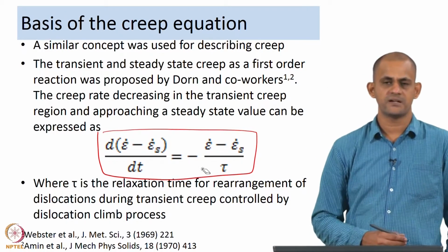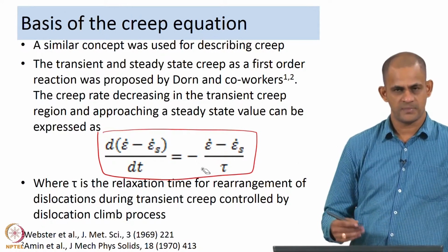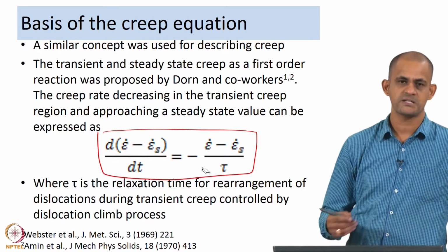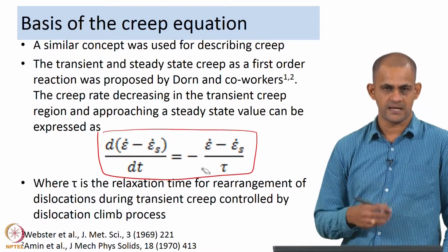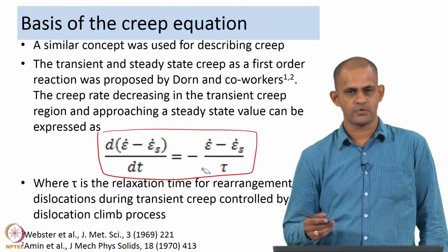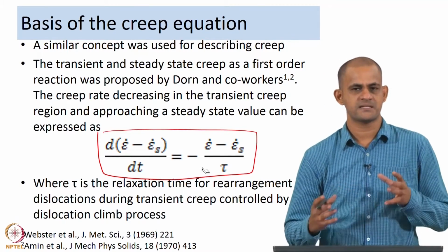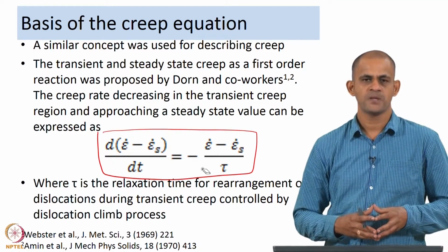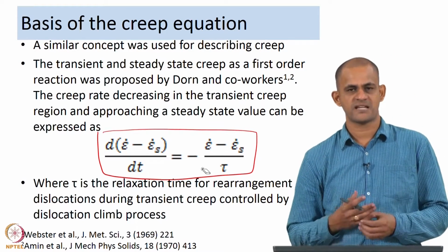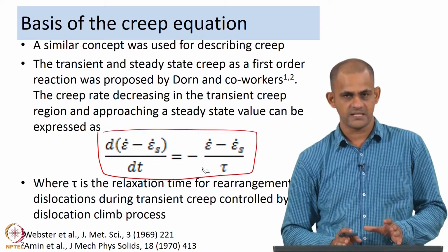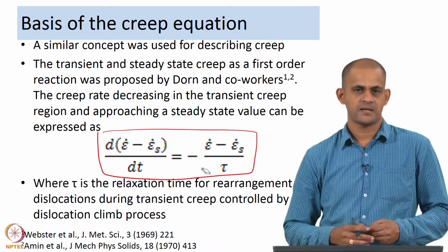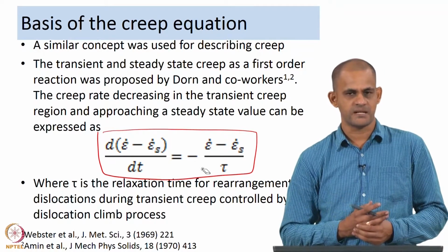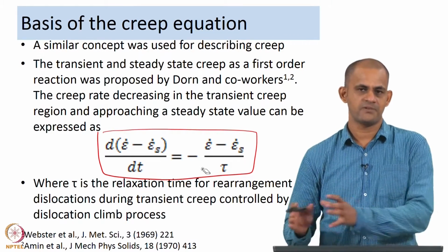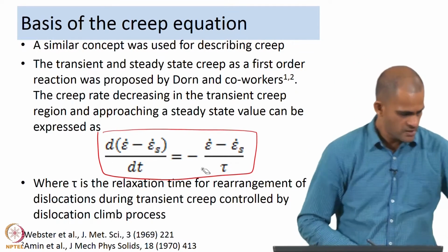The underlying assumption here is that the plastic deformation is being carried out by dislocations, and dislocation climb is a necessary mechanism for recovery to happen. When dislocation climb is happening, there is some amount of rearrangement of dislocations, and that rearrangement has a certain relaxation time tau. So, this is the equation, where epsilon dot is the instantaneous creep rate and epsilon s dot is the steady state creep rate. If we use this equation, we will be able to derive the entire creep equation.